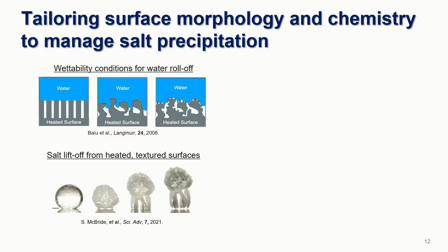And then if we look at salts, there was this paper last year which showed that as your water droplet evaporates and your salts are left behind, if that is happening on a textured surface and under a temperature gradient, your salts can form these legs. So your salt crystals essentially form these legs and eject themselves from these textured surfaces. And so looking at this, we said, okay, how can we modify our surfaces to get the water to roll off so that it's not staying there and evaporating to cause precipitation? And even if there is precipitation, can we get these salts to form the legs and lift off the surface?